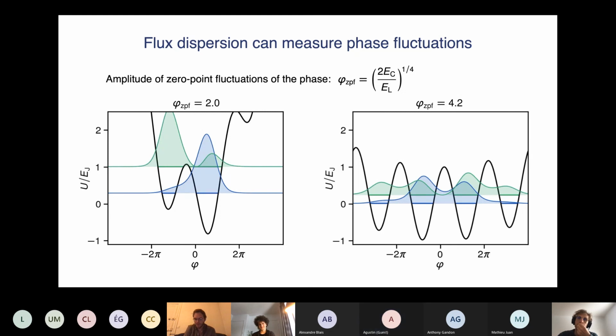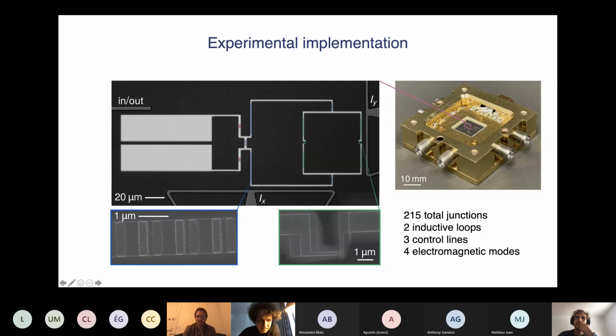That's a good question. We could reduce it a little bit more. Here I can say that we use these cross-style junctions as a way to really well control the area of these small junctions, and we could have gone further. We went to about 6 gigahertz, but we were trying to balance how low we could reduce EJ, which would also increase EC given the same plasma frequency. But we also wanted to make sure that the 2 junctions were not too asymmetric. Generally the problem is that as you make much smaller junctions, there is more noise in the area. So it would have been a bigger problem for us to have 3 gigahertz junctions that were 20% different than 6 gigahertz junctions that were 5% different.